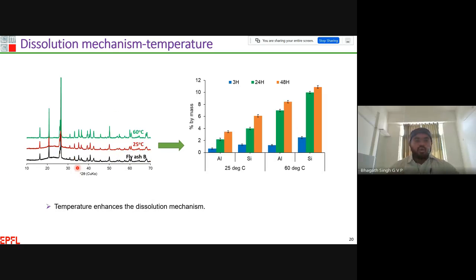And with respect to time, what happens if we increase the temperature? When we increase the temperature from 25 to 60 degrees Celsius, this is fly ash B, this is the reference sample. It clearly enhances the dissolution mechanism, and most of the fly ash is dissolved by 48 hours. But in the case of 25 degrees Celsius, we have to wait a much longer duration. At 25 degrees Celsius, you can see a steady release of reactive species into the solution, whereas at 60 degrees Celsius most of the fly ash is dissolved by 48 hours. Duration enhances the dissolution process, and temperature clearly enhances the rapid dissolution of glass and the release of reactive species into the solution.